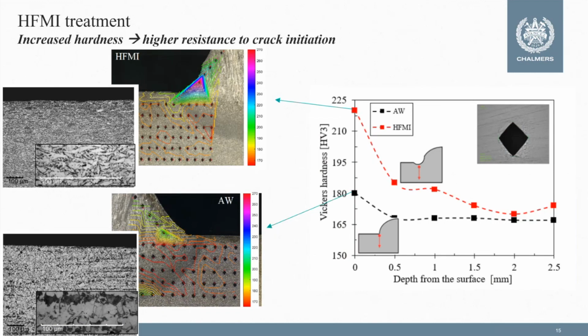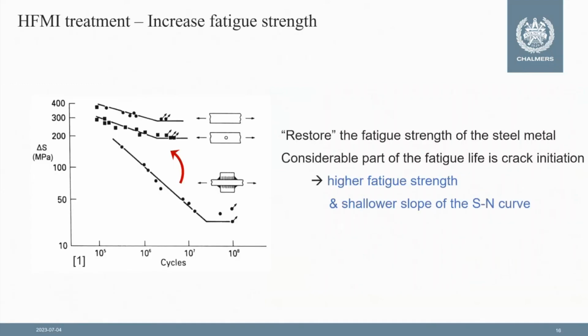And of course, the increase in hardness and the increase in local yield strength of the material would result in a higher resistance to crack initiation in this location, which also has an influence on the enhancement in fatigue performance. So all these three effects that are obtained from the HFMI treatment will result then in restoring of the fatigue properties from the lowered fatigue strength that we got due to welding into something that is close to the performance of the base metal.